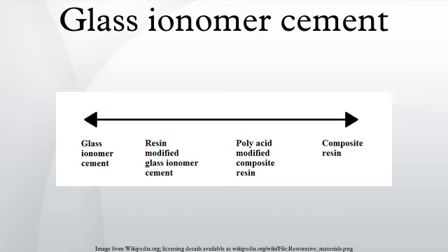The coefficient of thermal expansion of conventional glass ionomer cements is close to that of dental hard tissues and has been cited as a significant reason for the good margin adaptation of glass ionomer restorations. Even though the shear bond strength of glass ionomer cements does not approach that of the latest dentin bonding agent, glass ionomer restorations placed in cervical cavities are very durable. Nevertheless, microleakage still occurs at margins. An in vitro study has shown that conventional glass ionomer cements were less reliable in sealing enamel margins than composite resin. They also fail to eliminate dye penetration at the gingival margins.